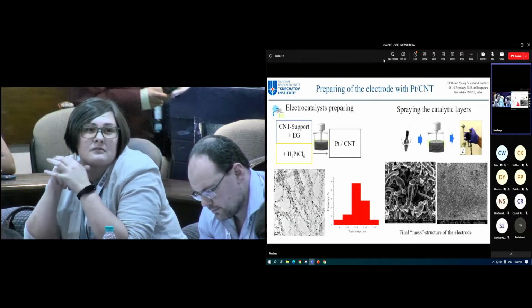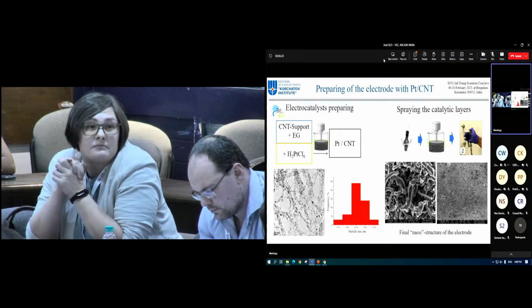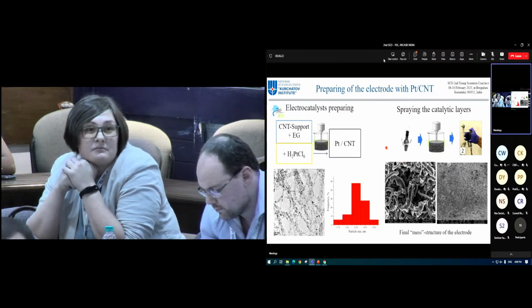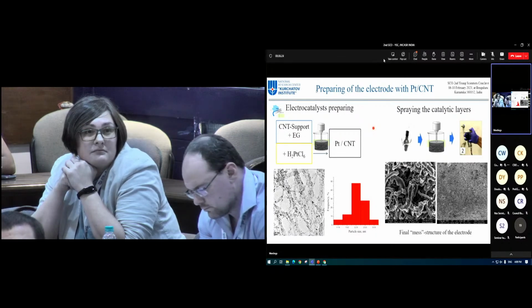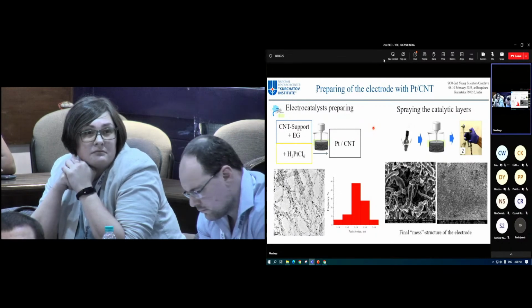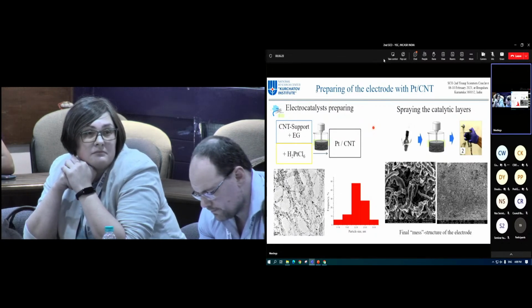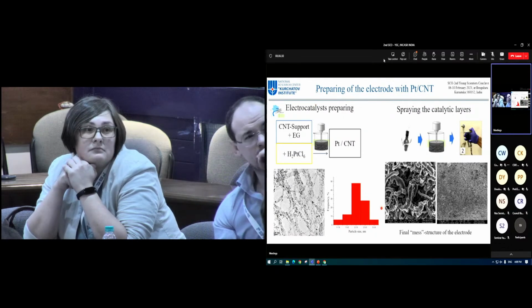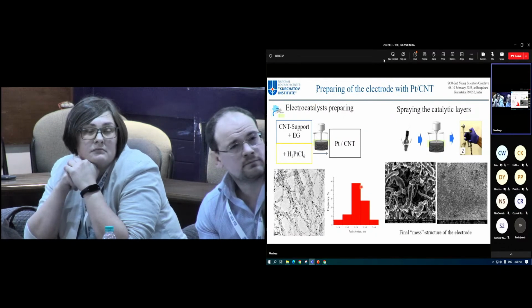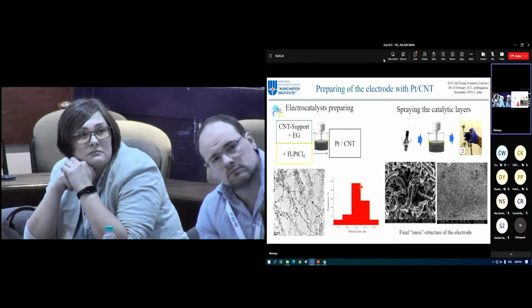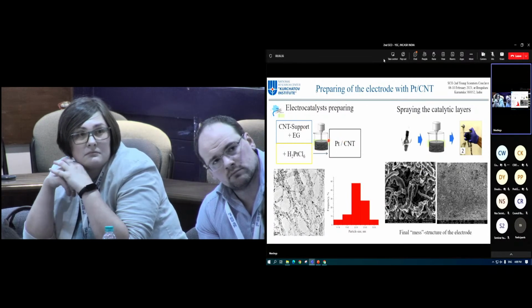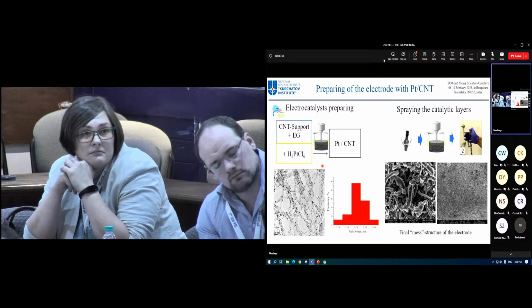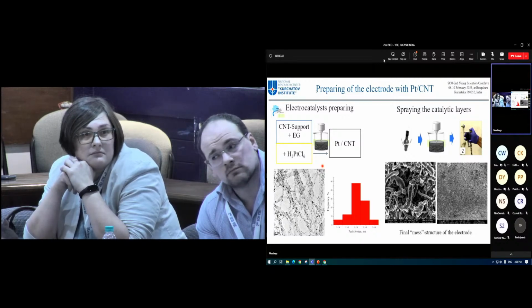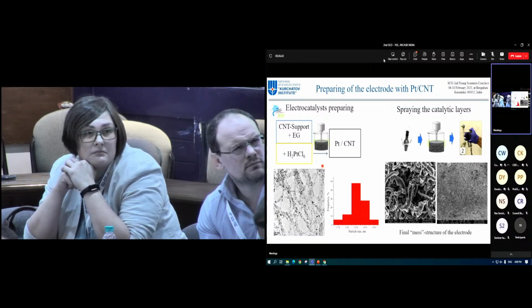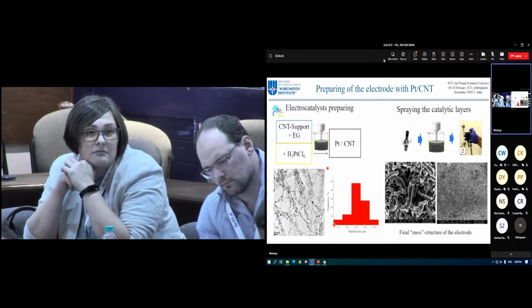The electrochemical performance of the catalytic layers is determined both by their chemical composition, type and content of platinum, and by their microstructure. This catalytic layer can be manufactured using a variety of methods. The use of nanotubes as a support using the standard synthesis method, the polyol reduction method, forms the catalytic layer shown on the slide. You can see the mass structure of it.